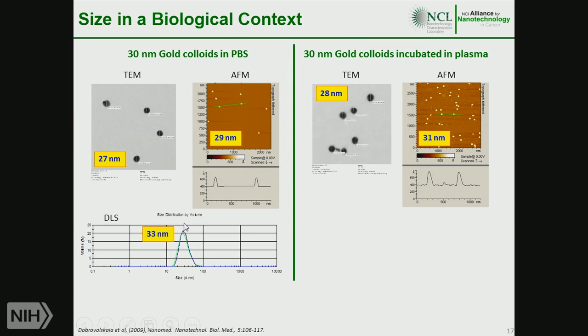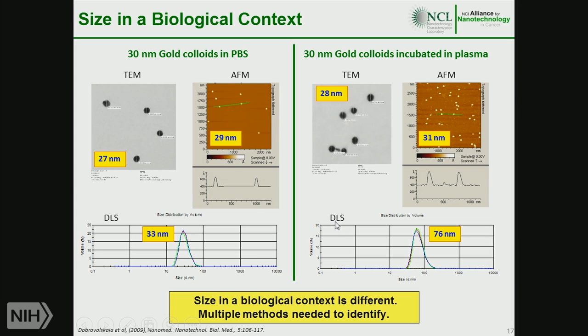Look what happens if we study these particles after incubation in human plasma. Transmission electron microscopy and atomic force microscopy, which look at the solid core of the particle, still show us the 30 nanometer size. But then dynamic light scattering, which shows the hydrodynamic size of the particle, shows that it almost doubles. We now see particle size increases to 76 nanometers. Why does it happen? In plasma, there are a lot of proteins. And these proteins can bind to the particle surface, and the particle gets larger due to the protein coating. And this soft size is not detected by TEM and AFM, but is detected by DLS. And this is the size at which these particles, when they are used in biological applications, are seen by our body. So our body does not see 30 nanometers. Our body will see a 76 nanometer particle.